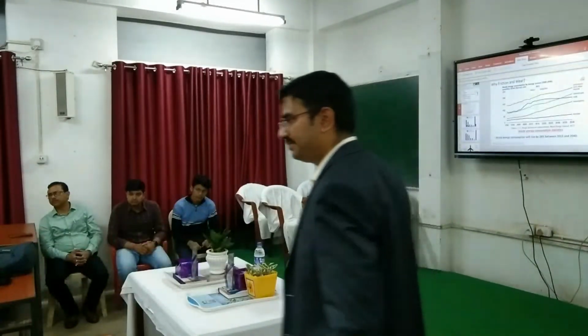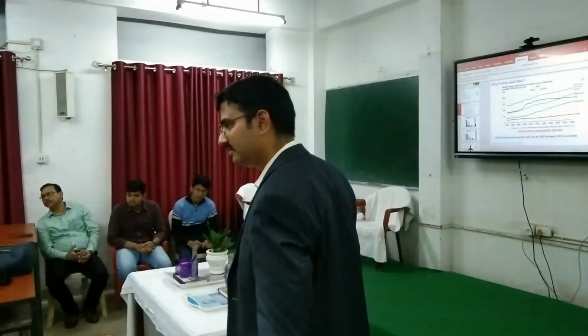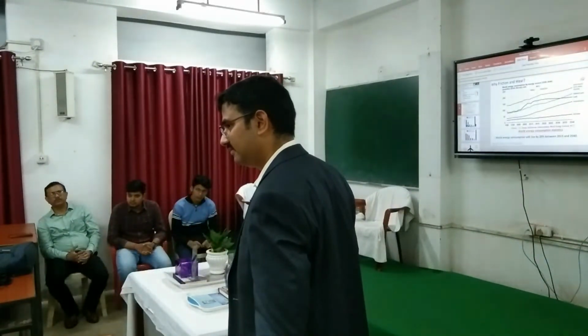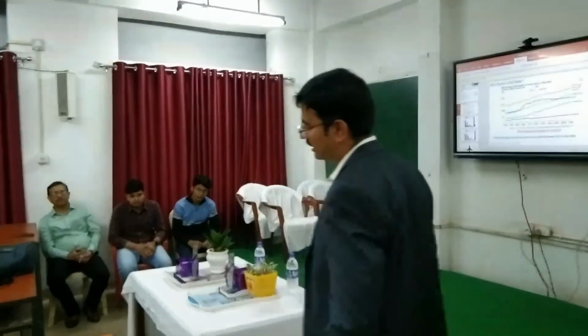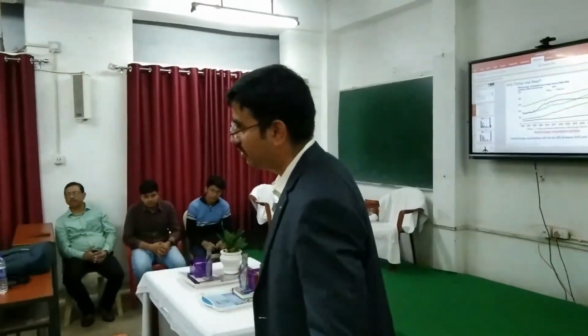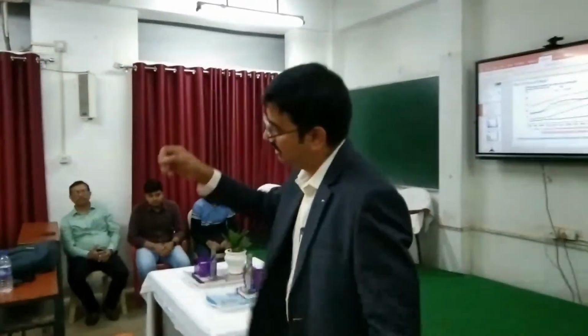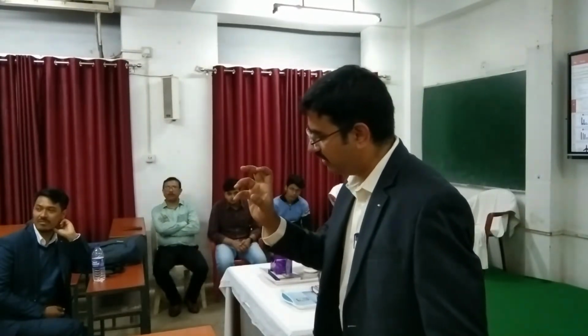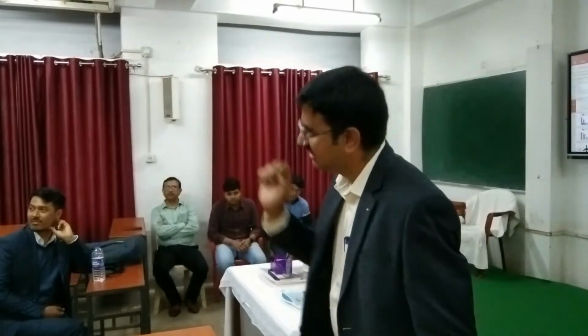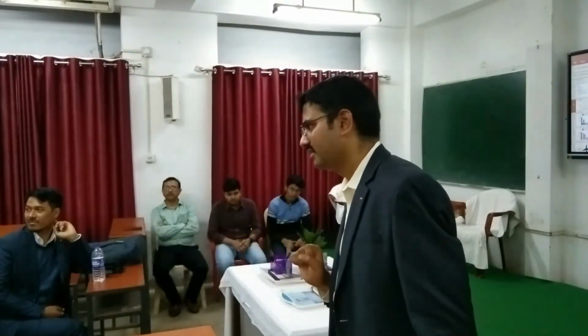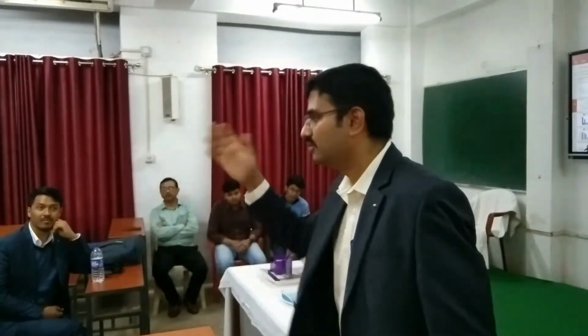Sir, another thing: can a ceramic material be deposited on a metallic surface? Yes, you can deposit it using plasma spray. You cannot do it by cold spray, because as soon as a ceramic impacts, it will undergo brittle fracture. Because of the way ceramic powders are made, you have inherent porosity and some cracks inside them due to manufacturing difficulties, and these emerge as soon as it impacts. If you are using plasma, you are melting them. It is a molten particle, so you won't have brittle fracture there. That way you can do it.